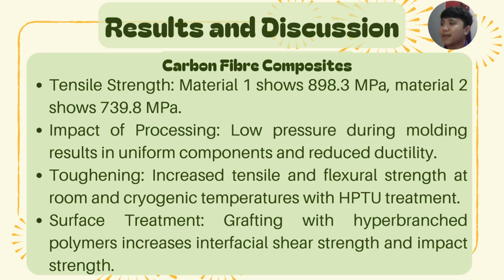Carbon fiber composites. Tensile strength: material 1 shows 898.3 megapascal, material 2 shows 739.8 megapascal. Impact of processing: low pressure during molding results in uniform components and reduced ductility. Toughening increased tensile and flexural strength at room and cryogenic temperatures with HPT treatment. Surface treatment: grafting with hyperbranched polymers increases interfacial shear strength and impact strength.